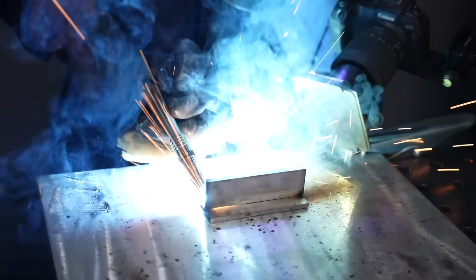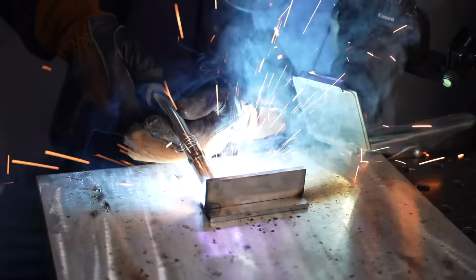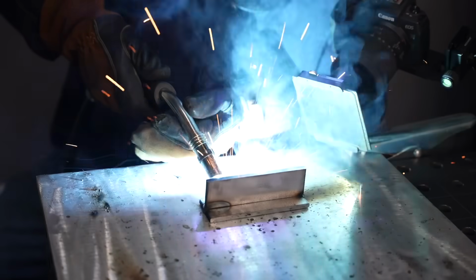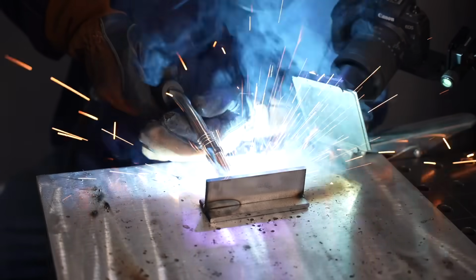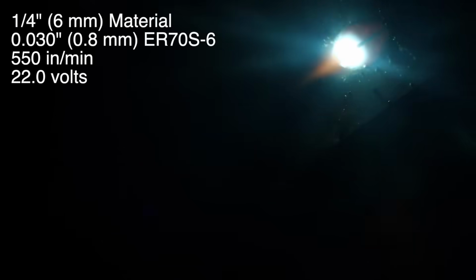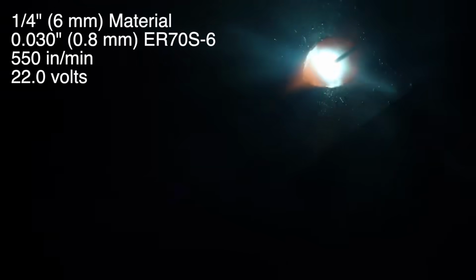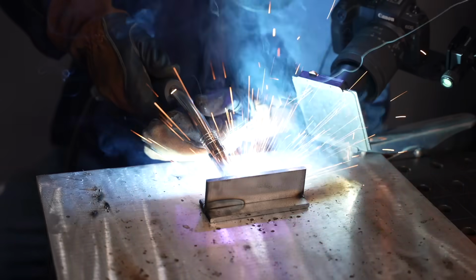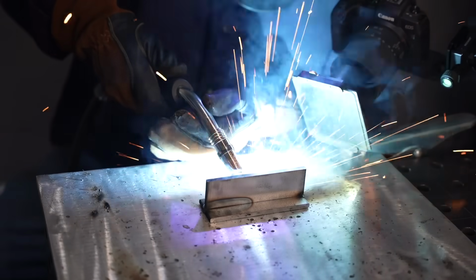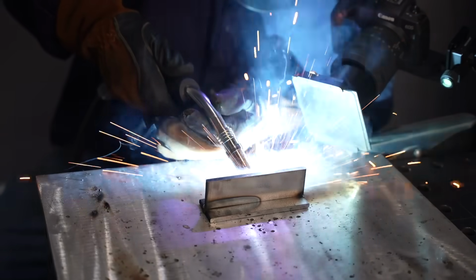So here with the 1/4 inch thick, you're getting a lot more spatter. You can see there's more sparks, and it's just a whole lot more aggressive because you're pushing so much amperage through that little wire, and it's just a little bit too much. They call that current density, is the technical term, but basically it's just a lot of amps for the cross-sectional area of wire. So for that reason, it's really not ideal.